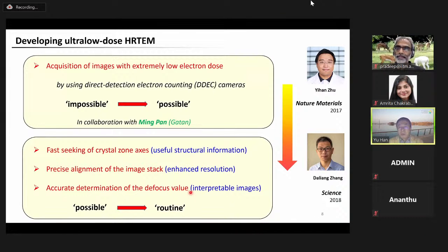And in the second step, we develop a suite of methods to improve the efficiency and the quality of the ultra-low dose HRTEM enabled by the new camera. These methods are about image acquisition and image processing. The first method, for example, allows us to quickly find the zone axis of the crystal in TEM so that we can minimize the electron dose used for the zone axis alignment, so that we can protect the structure from being damaged. And the second method can retrieve the impaired image resolution due to the specimen movement during the exposure, so we can enhance the final resolution of the image.